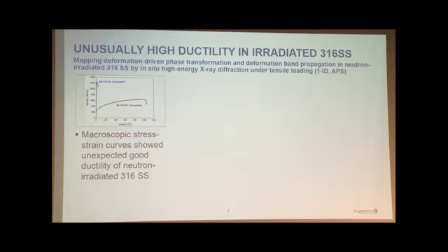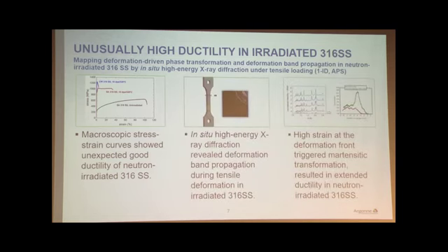But in fact, if we test a different stainless steel, this is again 316, irradiated to a very similar condition, if you look at this other 316, the ductility actually can go almost up to 30%. So what happened? It's all 316. How come one 316 has such better ductility than another one? And then we did an in situ experiment doing a tensile test with X-rays, and we have a very good answer for this problem.